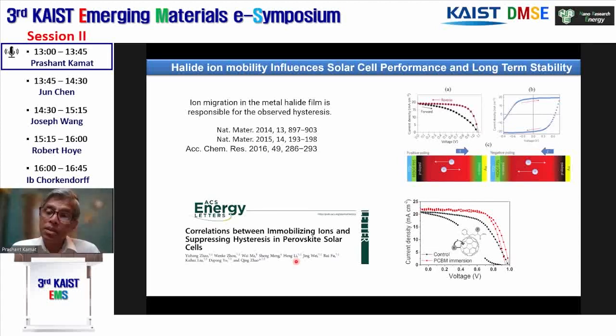People who are working in this area are able to get up to 1,000 hours, 2,000 hours with a minimal decrease. But if you want to have it for a practical device, you need to have a much larger time span. And one of the things early on, it was identified is what they call hysteresis.